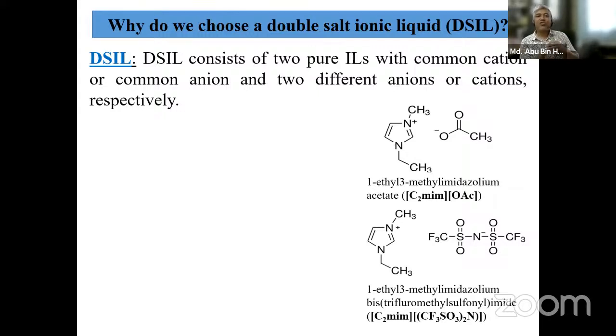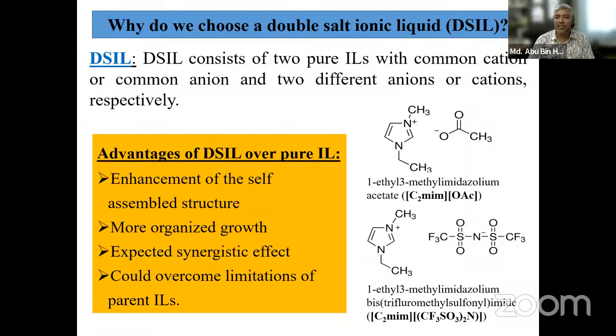A double salt ionic liquid consists of two pure ionic liquids with a common cation or a common anion. For example, here in C2-mim, the cation is common, and we can vary the anion, two different anions with widely varying properties. If we combine these two, we can have a mixture of ionic liquids, and interestingly, we can change the mole fraction of the ionic liquids. Say we can make a 25-75 mixture, or 50-50, or 75-25. In many different combinations, we can prepare double salt ionic liquids and check the properties and their impact on the growth of the zinc oxide nanoparticles.